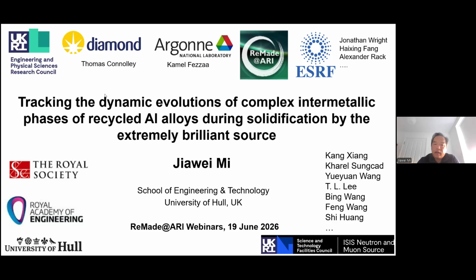about the recycling of aluminum-based material, in particular, how to use the extremely brilliant source, which is available in Europe, the ESRF, to track the complex intermetallic phases in the recycled aluminum alloys, and how we're using some kind of low energy, green approach to change those detrimental phases in order to make the recycled aluminum more available for